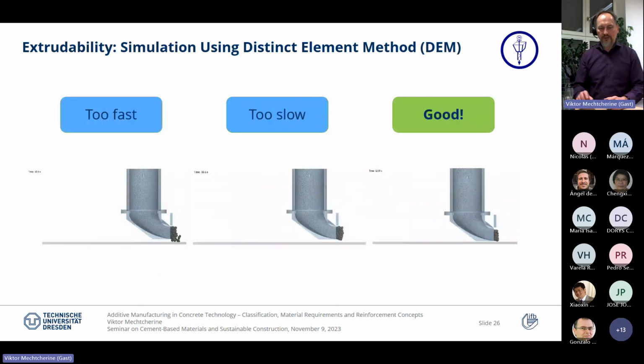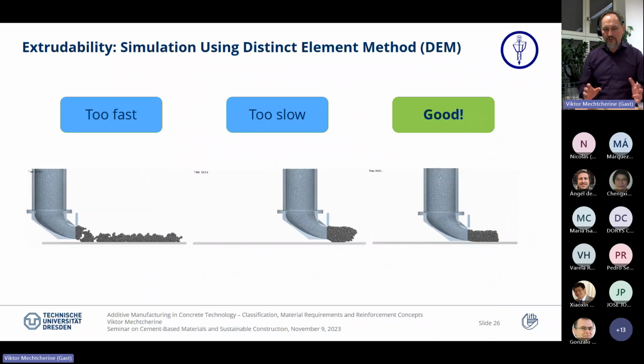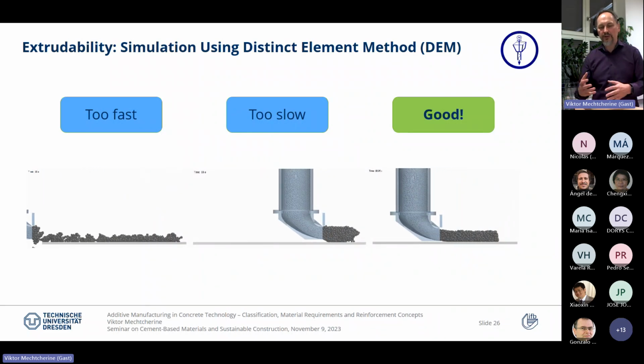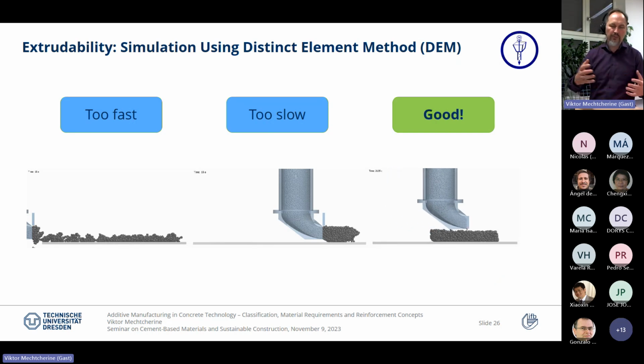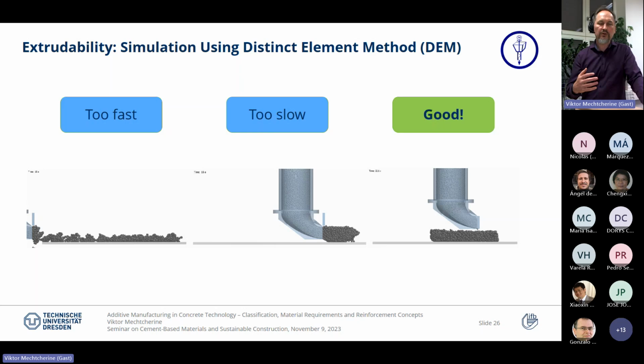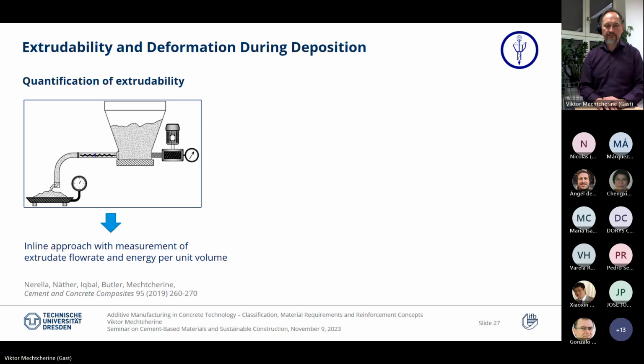Here is also a little demonstration that we can simulate how well the deposition rate of the material is coupled with the movement of the print head. On the right hand, it seems to be a good coupling, and in the other two examples, too fast and too slow, it doesn't bring a good result. And this is really important, that you always adjust the movement of the print head, which is performed by some operating machine, it can be a gantry system, a robotic arm or whatever else, and the delivery rate of the material.